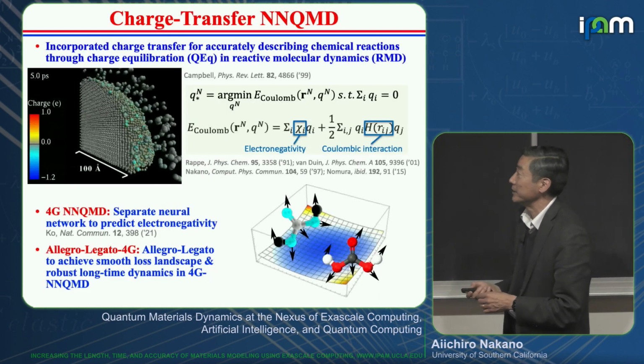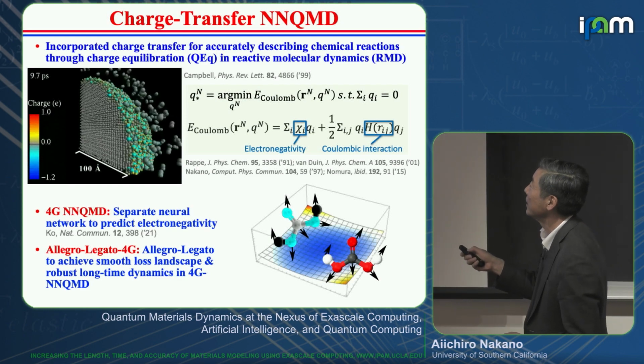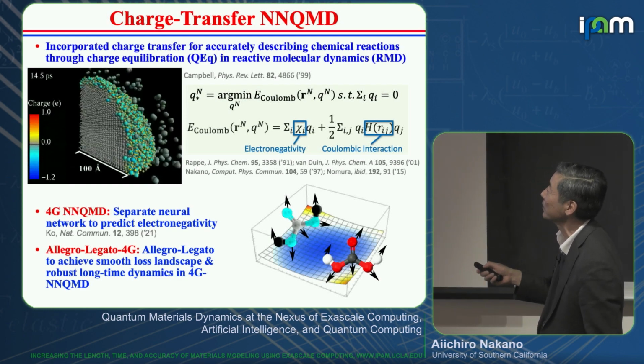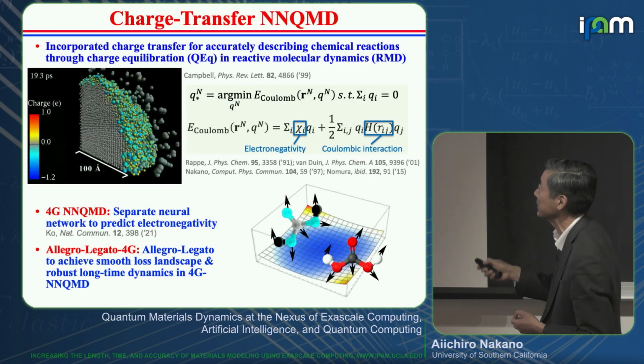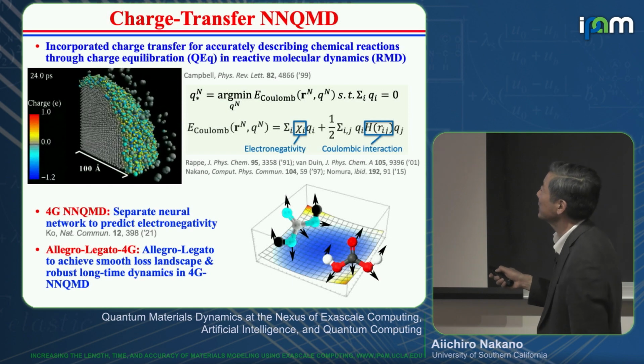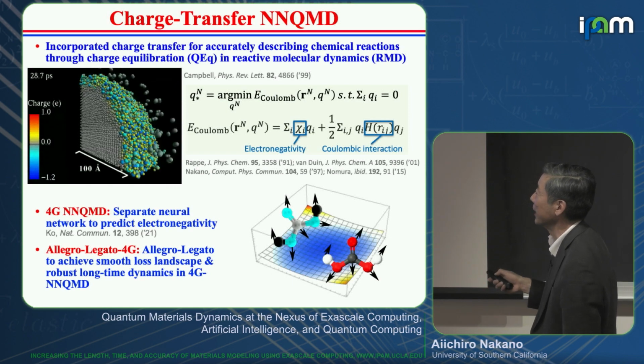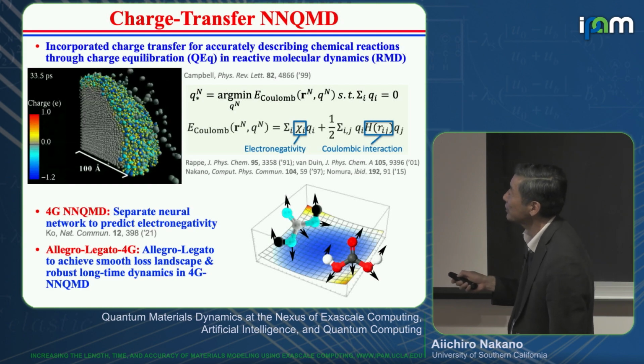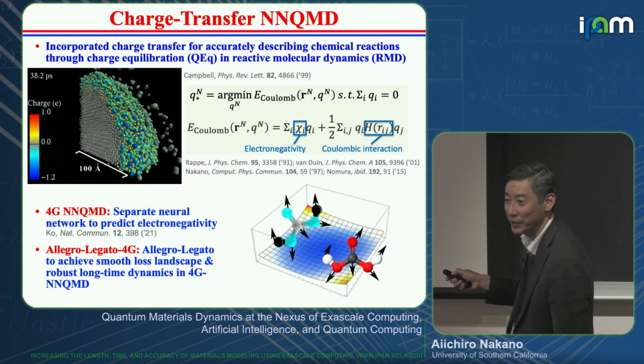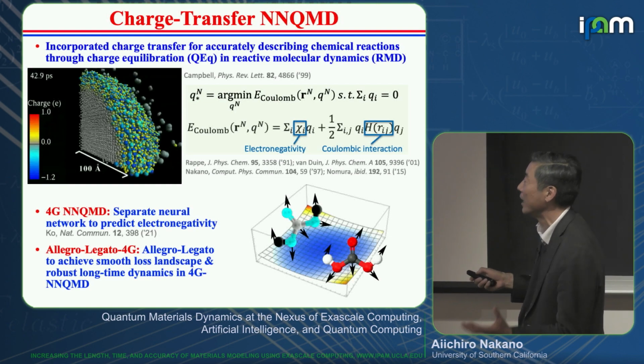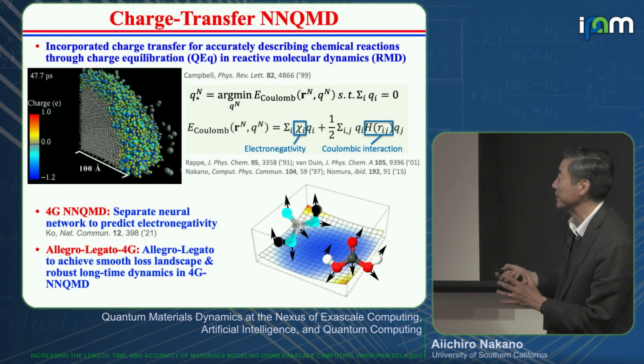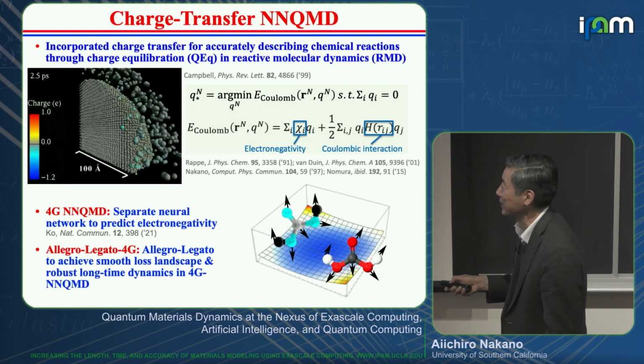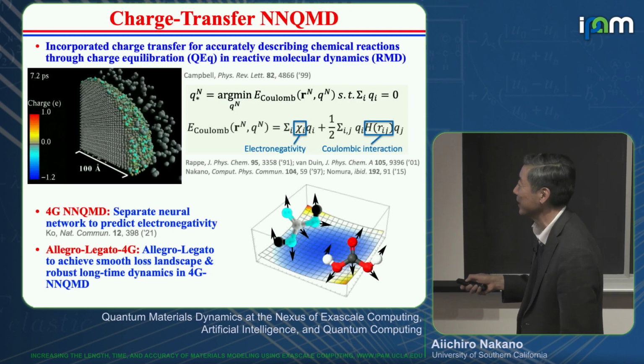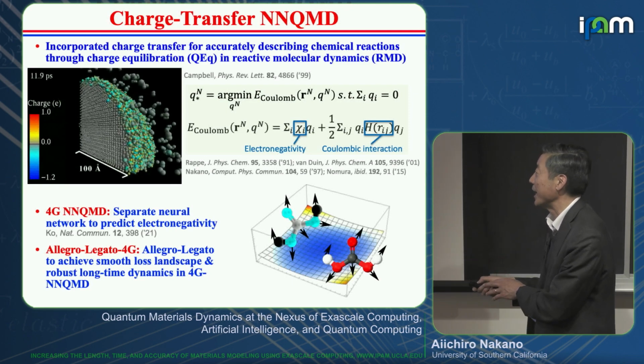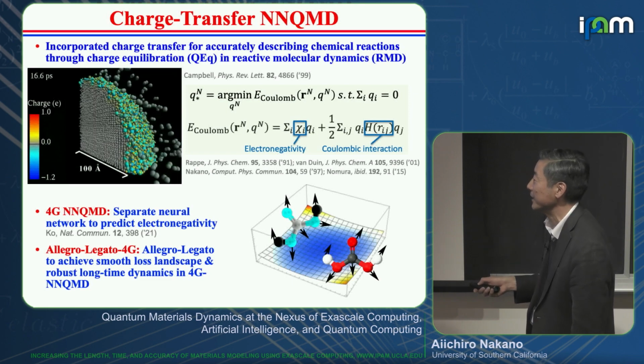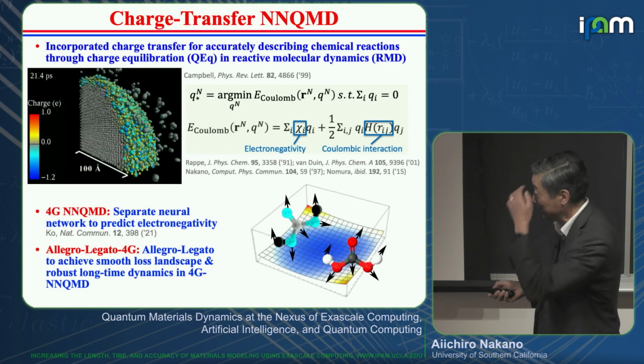Another thing we implemented is to incorporate charge transfer to accurately describe chemical reactions through charge equilibration in reactive molecular dynamics. Basically, given the electronegativity, the charge is obtained at every MD step. This shows the charge transfer from aluminum to oxygen during the oxidation of aluminum nanoparticles. We incorporated this charge equilibration part into the neural network, and this was named by another group the fourth-generation NNQMD. Then we apply Allegro-Legato to achieve the same smoothness and robust long-time dynamics within this 4G neural network.